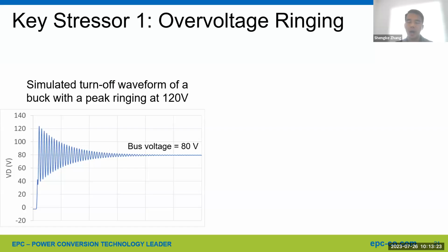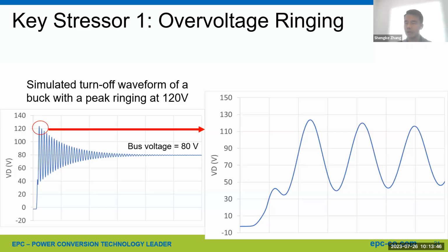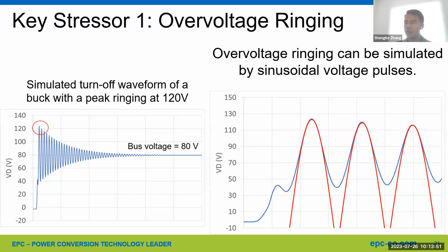So here shows the turn off voltage waveform again of the buck converter shown previously, where you probably noticed the key stressor is the over voltage ring. Let's first focus on the first 3 rings with the highest amplitude, which I believe have the most impact on GaN reliability. Here's the zoomed-in image of the first 3 rings. So we found that the over voltage ring can be deconvoluted into individual sinusoidal shaped voltage spikes, as shown in the red curve right here.